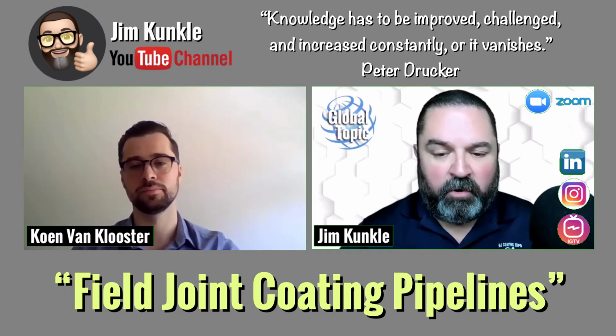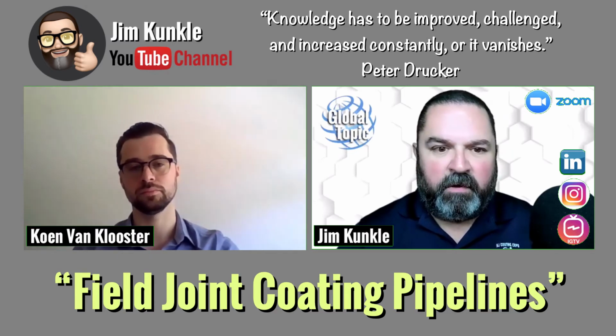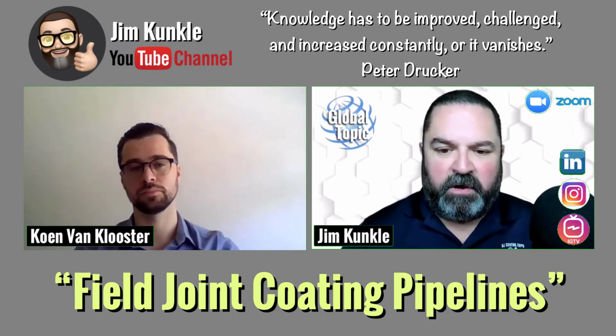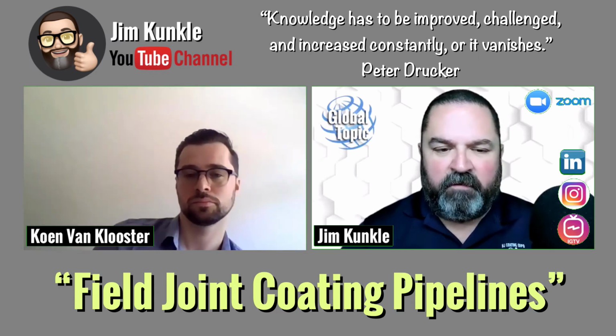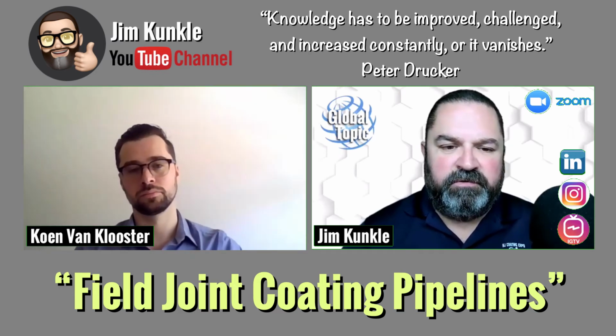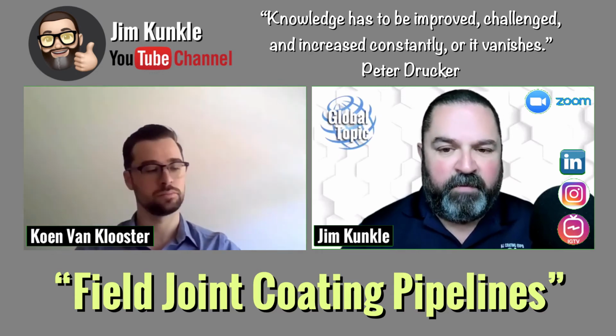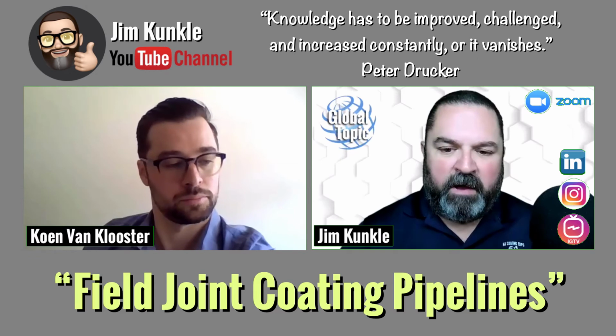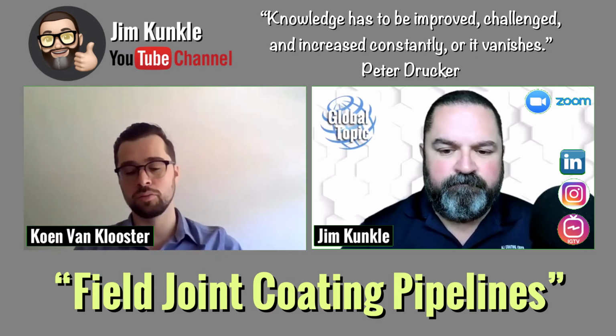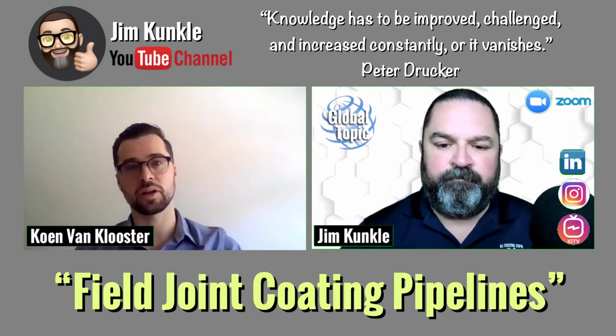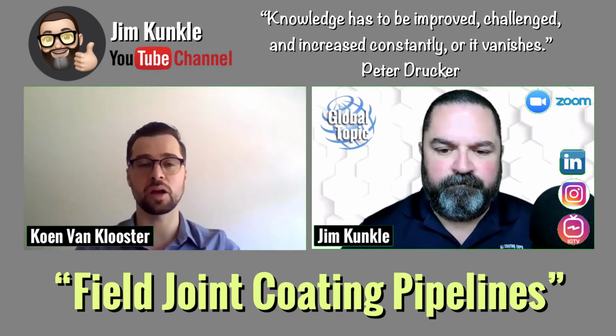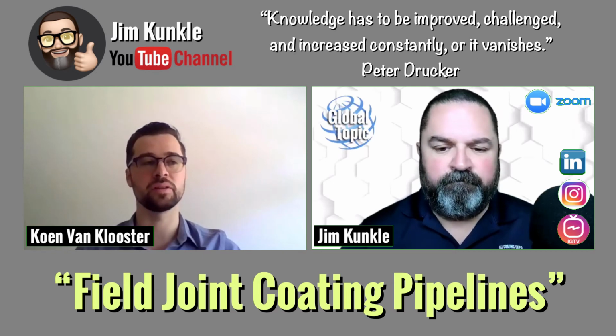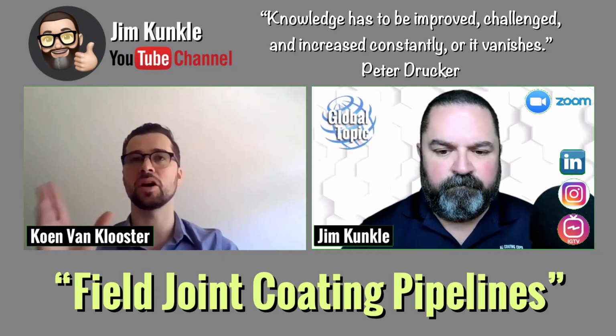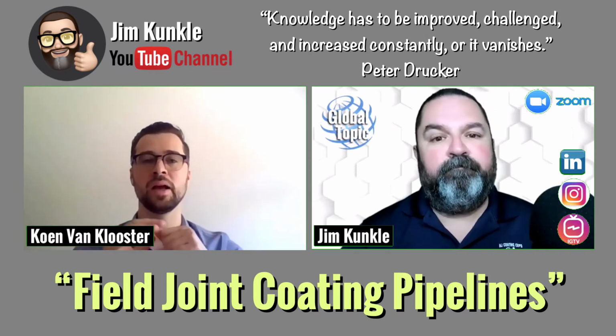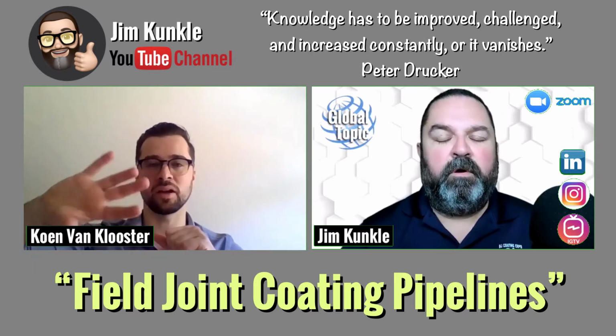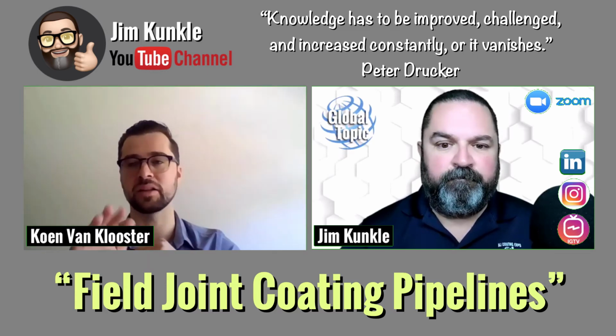So earlier in your covering of the topic with induction heating, you mentioned fusion bonded epoxy, FBEs, are heavily used, obviously, but in relation to the field joint coating systems like an FBE, how is it applied on the pipeline on the field joints? So the FBE, the epoxy powder, is applied to the pipe with electrostatic guns. The electrostatic part helps with the adhesion of the powder to the pipe, and these guns are generally mounted into a frame that's lowered over the pipe, and then there's a mechanism in there that rotates the row of guns along the pipe to create that even coat.